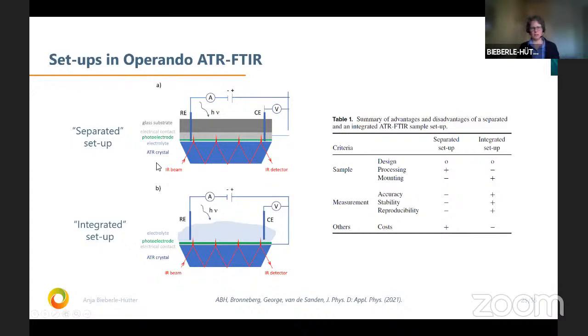So as I said, the two papers that I showed before use what I call a separated setup. So they have this crystal here, and then have the sample actually flipped on top of it, and then have very little electrolyte. And this is actually a problem for the reproducibility and stability of the measurement. Another setup that we have followed lately is to really deposit the films on top of this ATR crystal. The main problem is the cost here, but you get much nicer and more reproducible measurements.